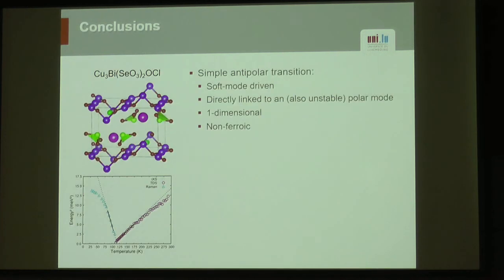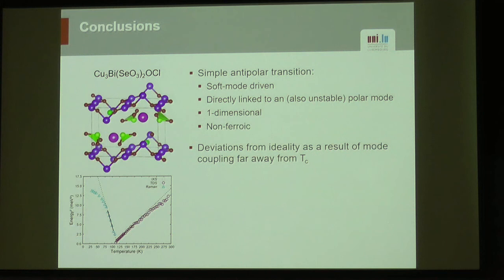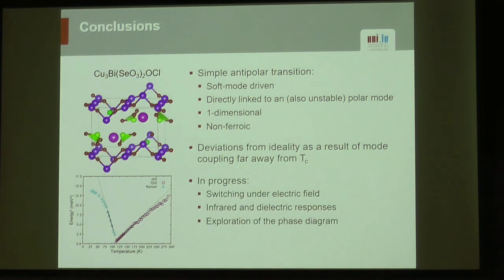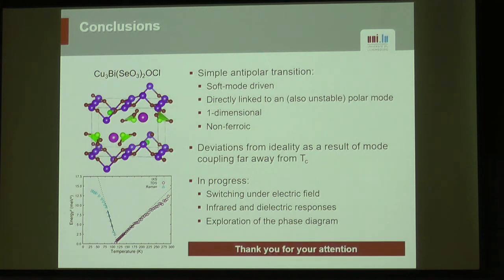So with this, I'm wrapping up with this example. So again, I would argue that in spite of its complexity, this crystal gives us a very nice example of a phase transition. It's soft mode driven. It's one-dimensional. It's non-ferroic. This also is an important point. I pointed out some deviations from the ideality as you move away from TC, but not in a very critical way. And obviously, the work in progress are the switching on the field, which we still definitely need. The infrared and the dielectric responses, this is also ongoing. And then generally speaking, the exploration of the phase diagram, including with pressure. So with this, I thank you for your attention.